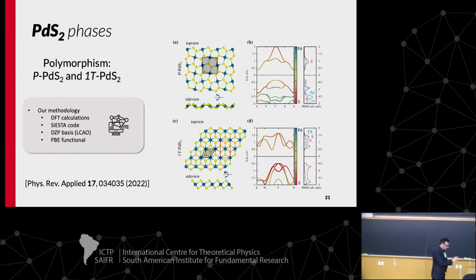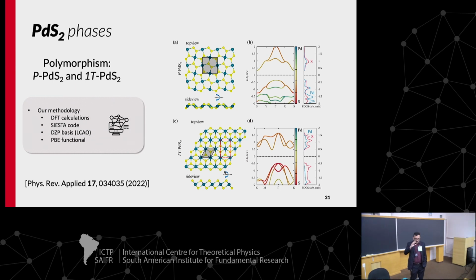When we study MoS2, we usually do the exfoliation of MoS2 with lithium intercalation, and with intercalation they have a phase transition, and when we have the phase transition, we include a lot of defects in this material. So experimentally, when we see the material, we have a lot of defects. Actually the hard part is not how to make the defect, but what kind of defect we can calculate the occurrence of with the formation energy. So you can calculate. Okay.